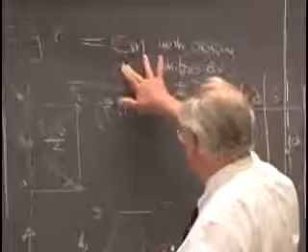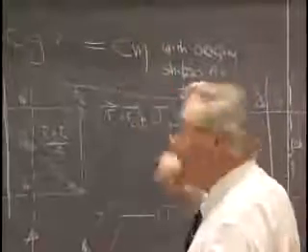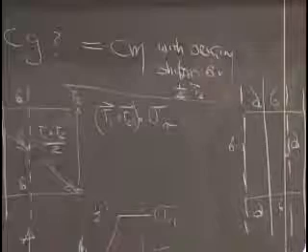Proceeding logically, we would take CM and replace the mirror plane by a glide. When we do that, we have a consistent group, but it turns out to be exactly the same arrangement of symmetry elements and exactly the same pattern as CM, but with a little nudge over along T2 by 1/4 of that translation.